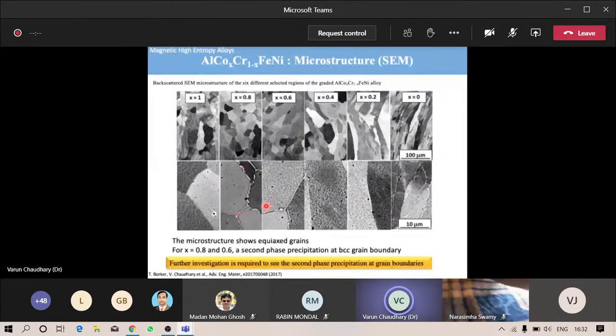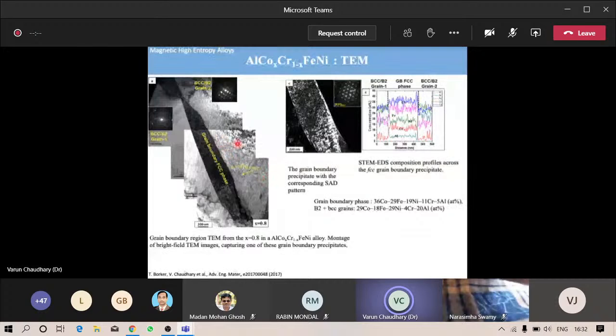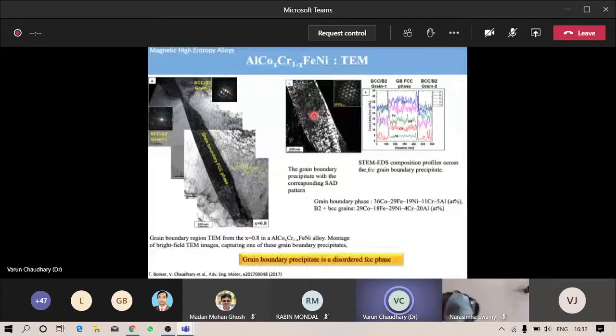To find out what that is, we investigated these samples with transmission electron microscopy and found that this grain boundary phase is basically face-centered cubic. By SAED, it was confirmed that it is a disordered FCC phase. We also measured the composition across the grain boundary. This FCC phase has more iron and cobalt and less aluminum.